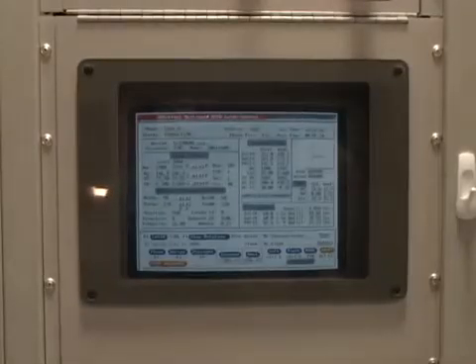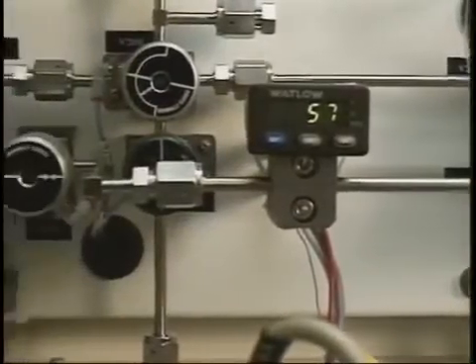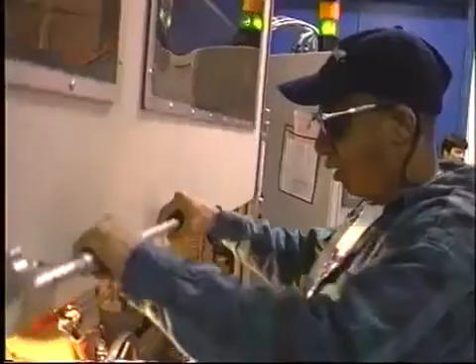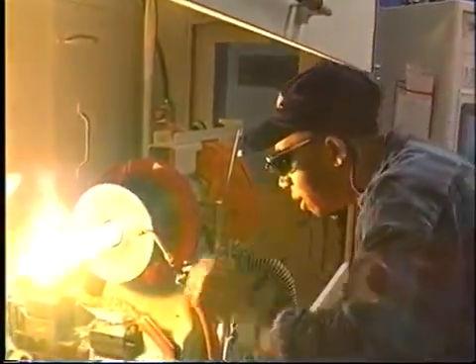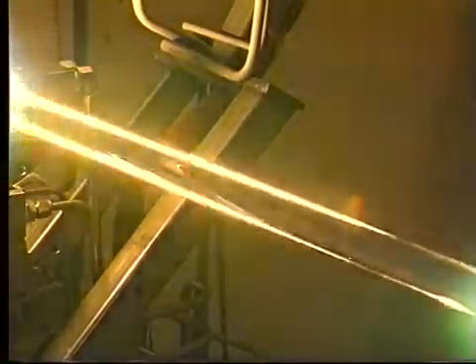Computers precisely control all process parameters, including the chemical delivery, torch speed, and temperature. The number of passes of the torch and the chemical composition used depend on the specific type of fiber being manufactured. After deposition, the tube is collapsed into a solid rod or preform by increasing the temperature of the flame and decreasing the speed of the torch. The preform is then analyzed to measure its refractive index characteristics and core diameter. To bring geometrical dimensions of the preform to final specifications, the outer or cladding region of the preform is further increased by collapsing a second silica tube onto the outside of the original preform.